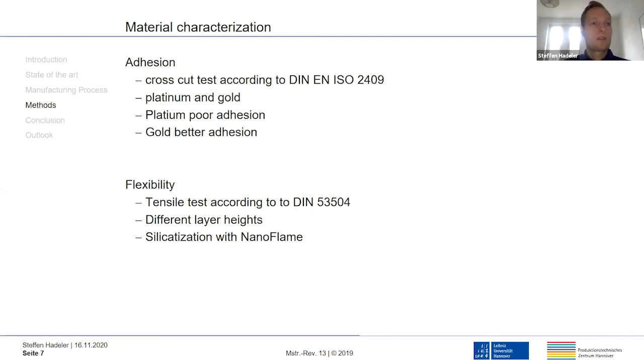Based on all these results of the adhesion test, all subsequent investigations were carried out only using gold as the coating material. After this, a tensile test was performed to examine the flexibility of the conductive coating, and it was examined at which elongation a conductivity of the coating is guaranteed. Different layer heights were tested, and the influence of silicatization was investigated, because silicatization has been shown to improve the adhesion of polyamide to PDMS.